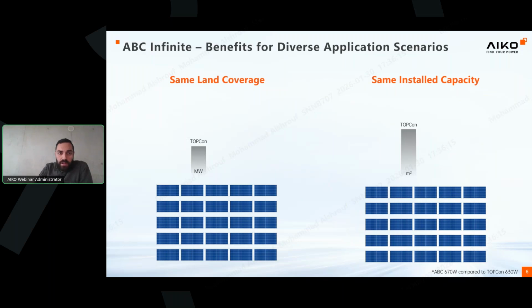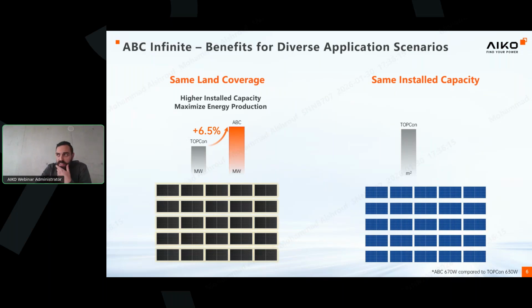When it comes to these panels, we can go in two directions or two scenarios. First one, we can have the same land coverage. What does it mean? You utilize the same land, but by using an efficient panel, you can boost the generation unit, the DC capacity. It can be increased by 6.5%. So as I said at the beginning, each panel will contribute with 35 watt more, and as a percentage, you increase the DC capacity by 6.5%. This is a big advantage to enhance the yield and enhance the business case of the solar projects regarding it's like rooftop or utility. And this is always a good approach if you don't have limitation on the DC capacity on the grid side. And then you can increase the DC capacity.